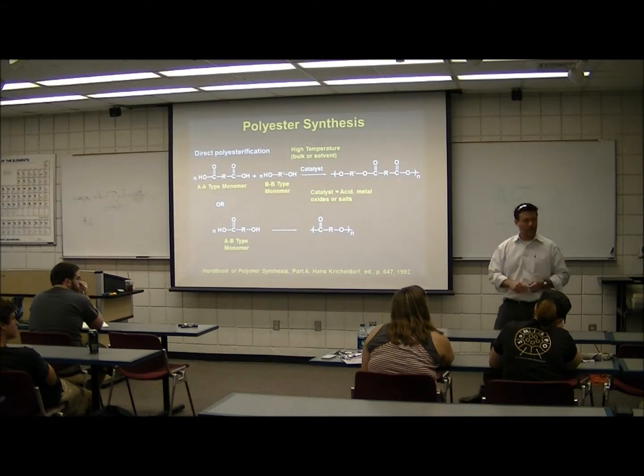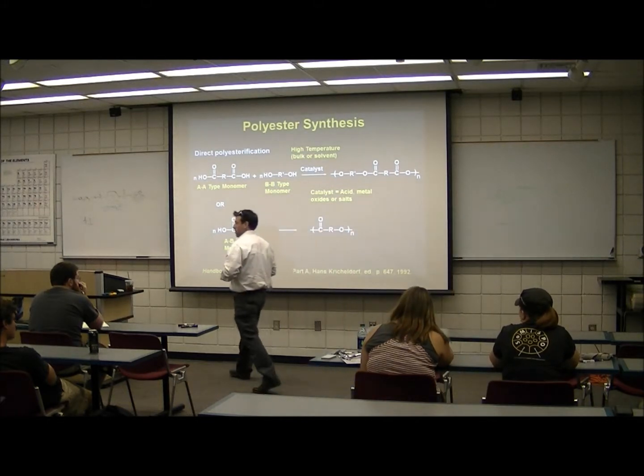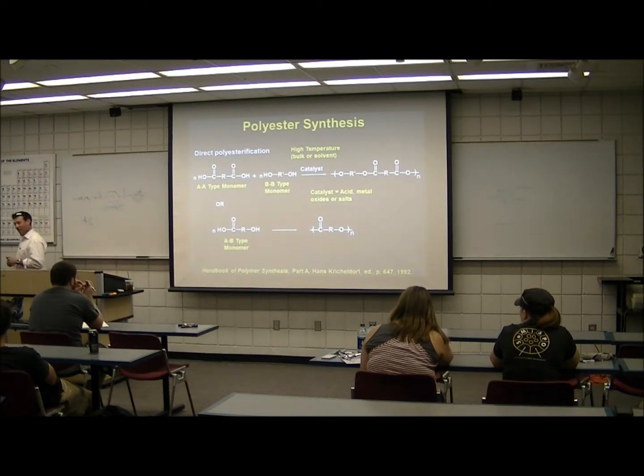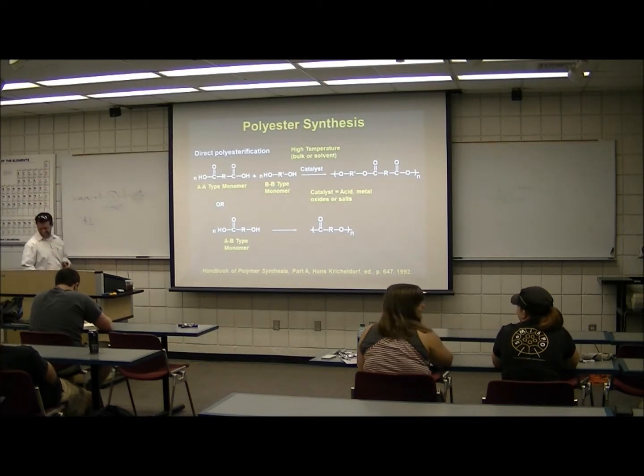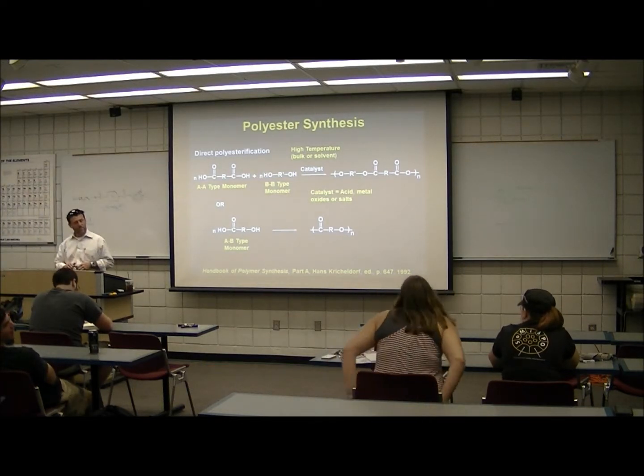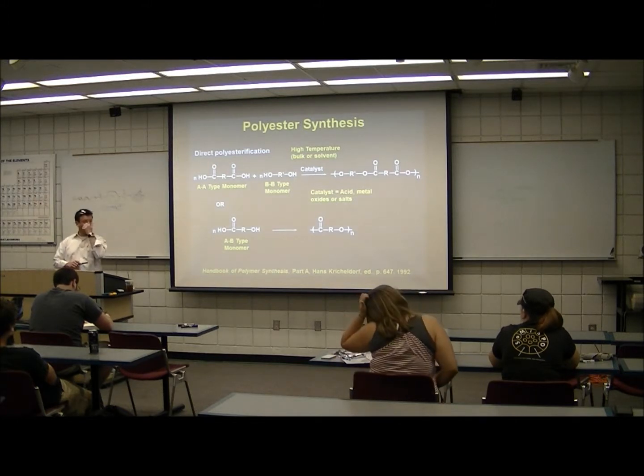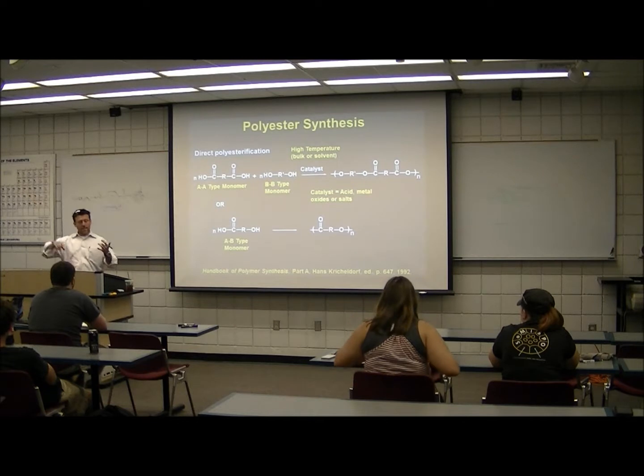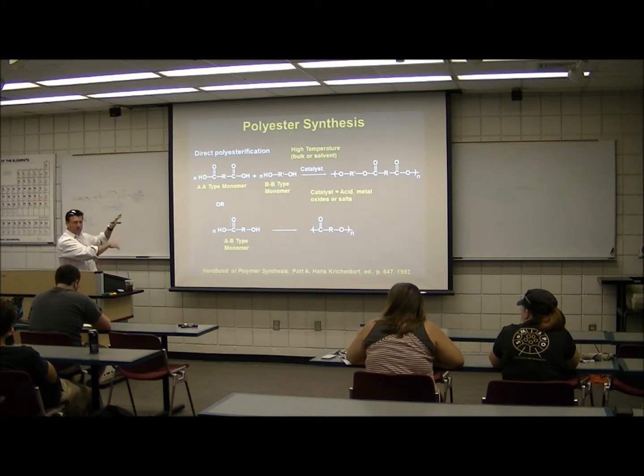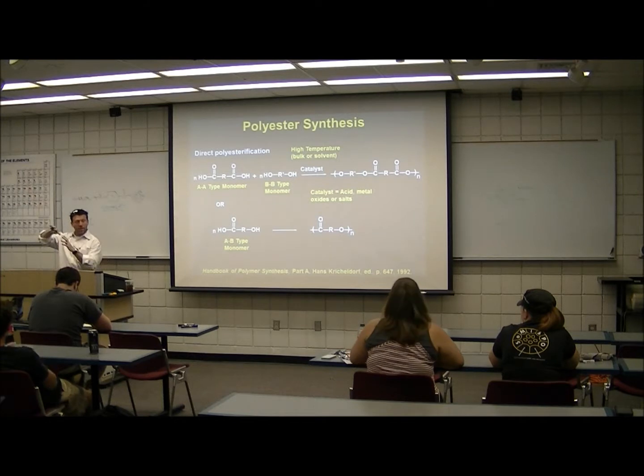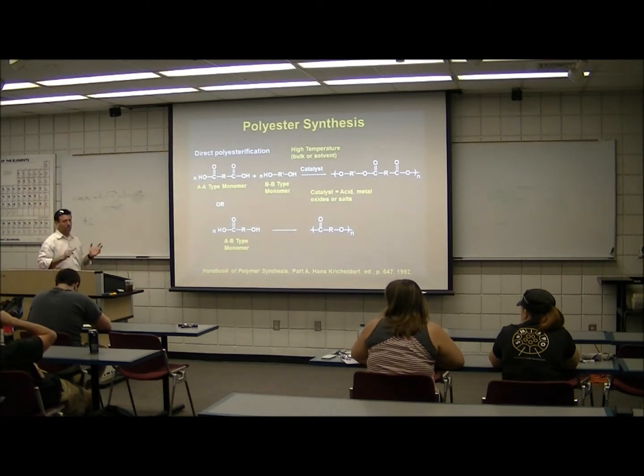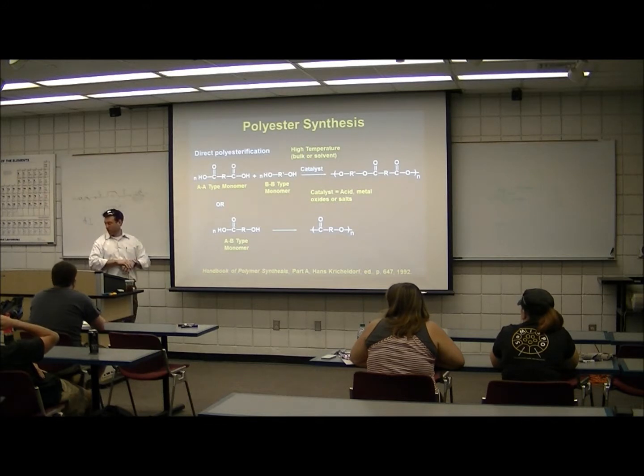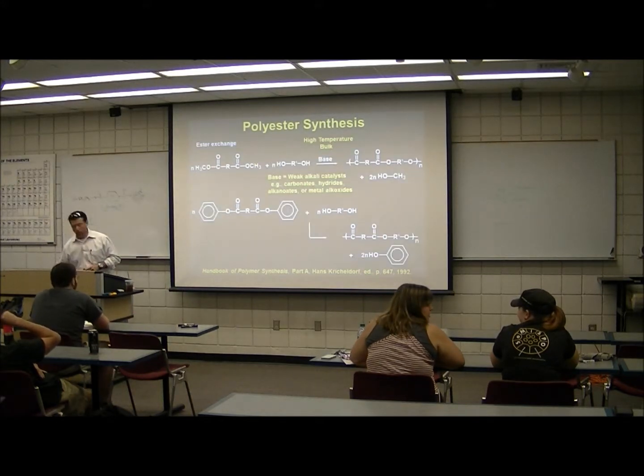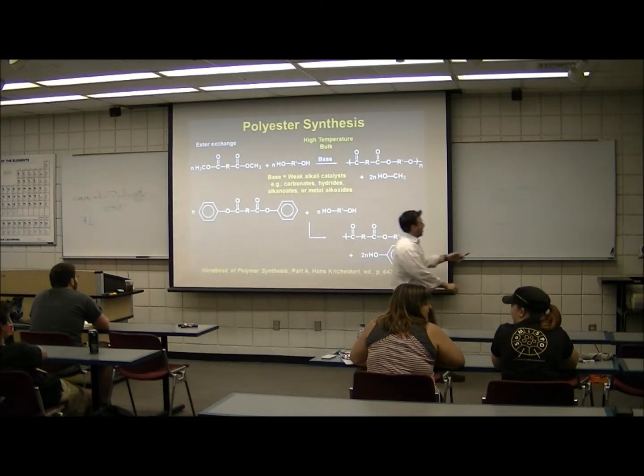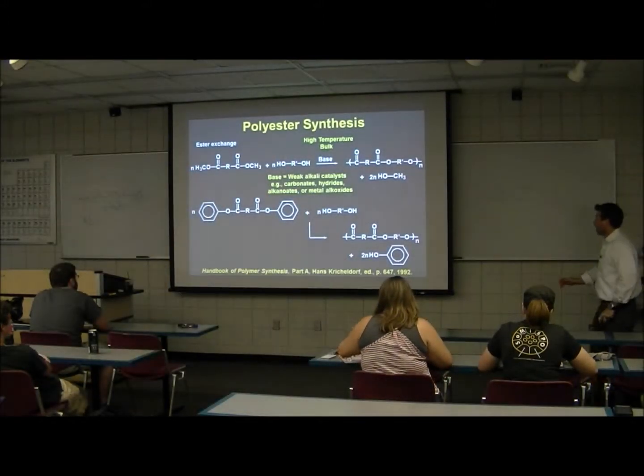Esterification is an effective, it's even a natural process, right? People in California should be going, yeah, dude, esters, they're all natural. Right? Right, Greg? Absolutely. And they process PET to about 500 F. Oh, yeah. Yeah, and absolutely. Like 510, and it doesn't char at all, and it comes out nice and clear. It has to be dried to less than 50 ppm, and it has to be under a certain head of nitrogen or argon or something like that. But it's possible. But throw some oxygen and water in there, and everything goes to hell quick. I've done that. So, this is just one of those things that people miss. They don't get that, because we always talk about high temperature.